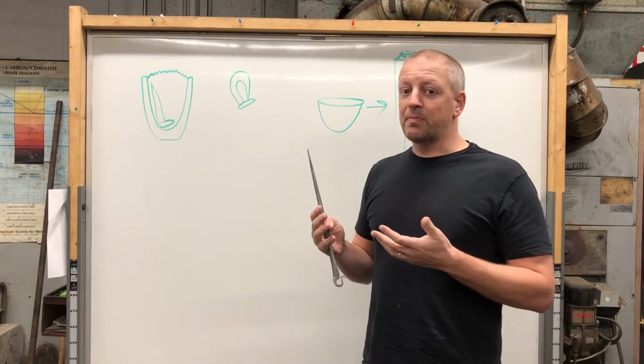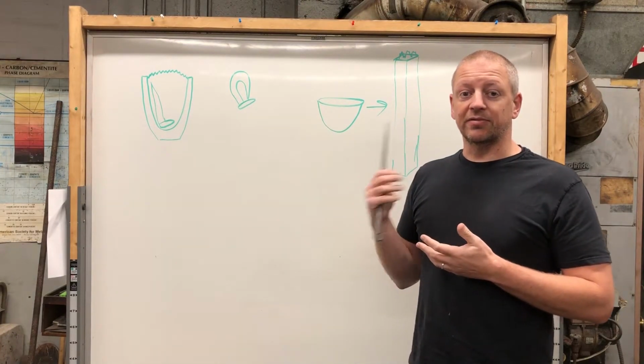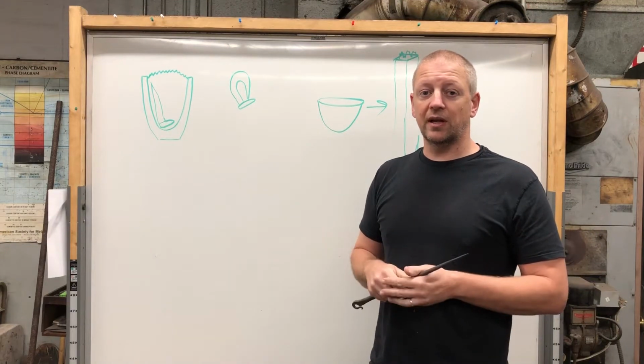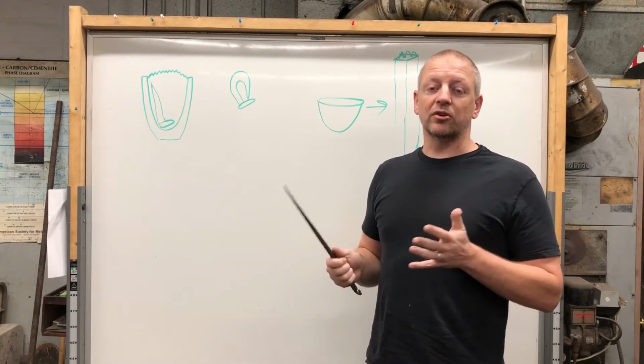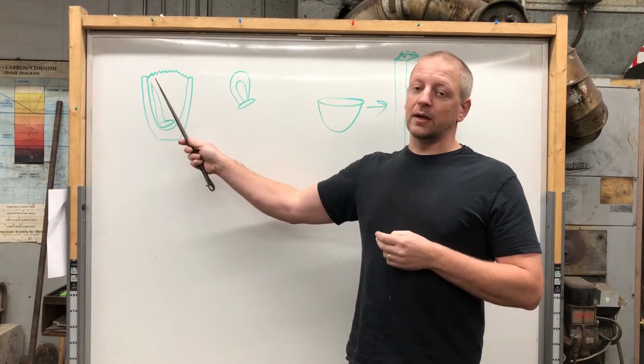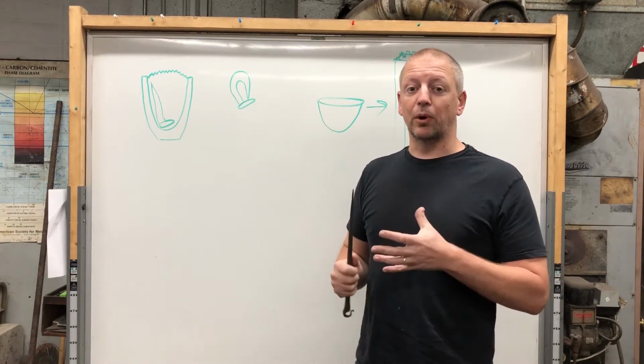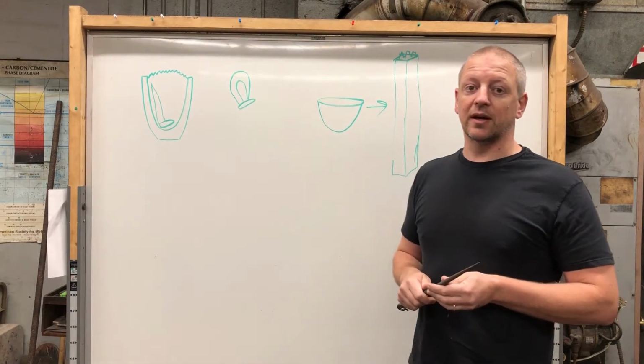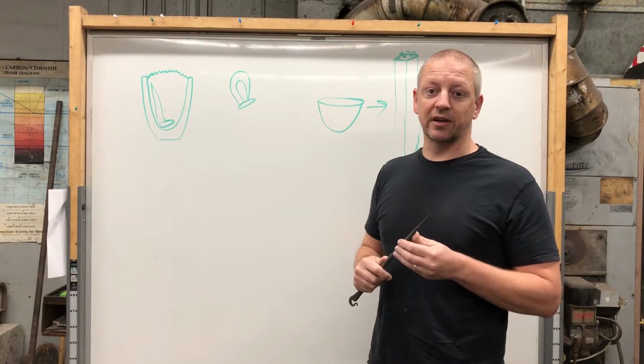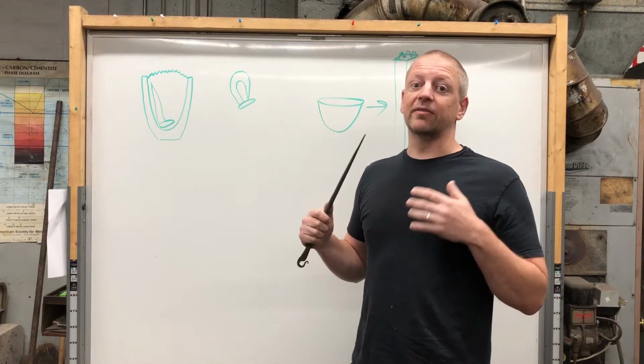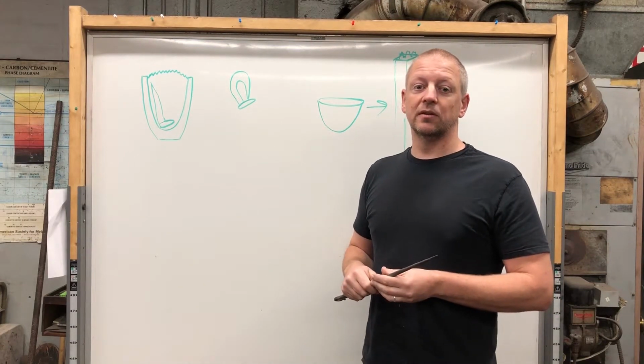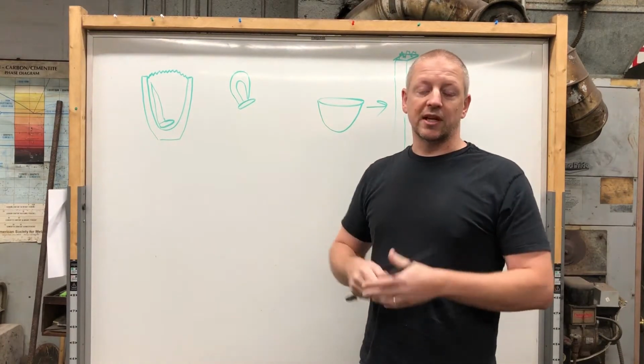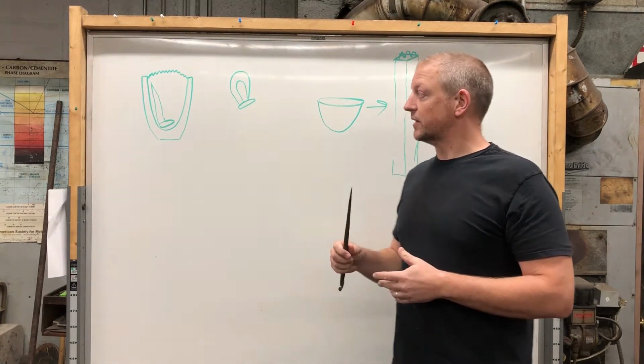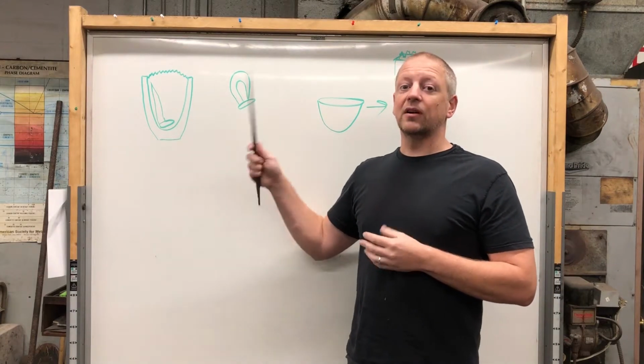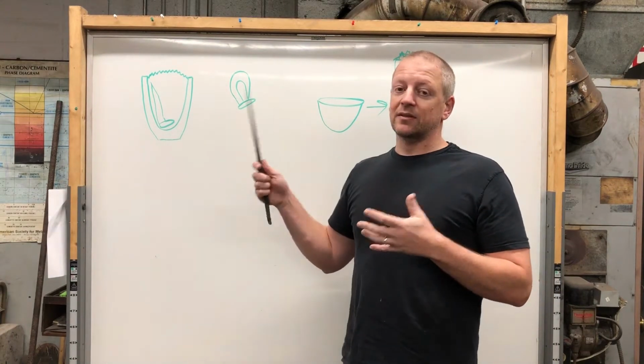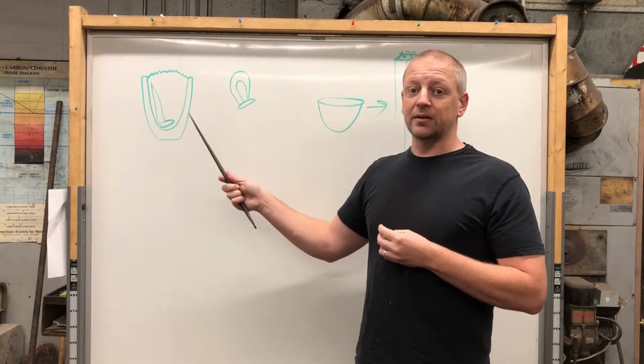And I do my best to keep a fairly neutral flame going in there, but in reality, there's no such thing as a neutral flame. If you've got exposed iron, it's going to oxidize at those kind of temperatures. It's just reactive enough. It's going to happen, unless you have a super carburizing environment, as you do in, say, a bloomery stack, something like that. So I got a lot of oxidation. A lot of that oxide ends up in the melt.